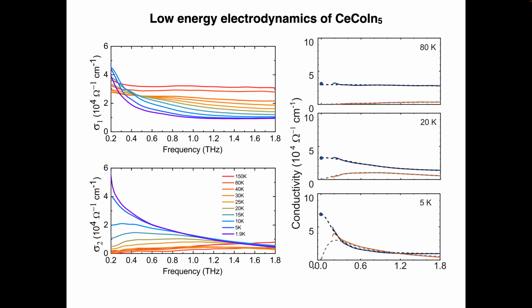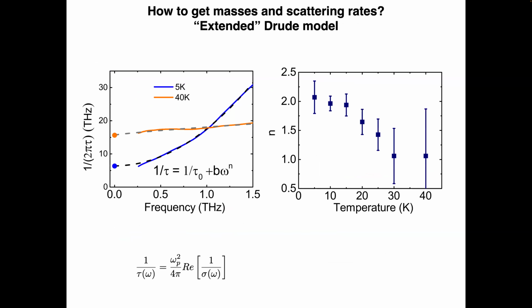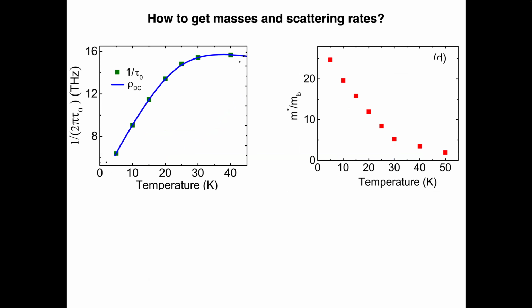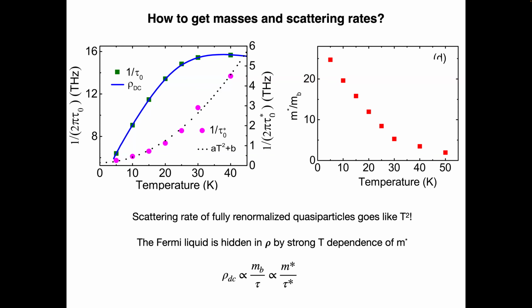And so you could infer from this, again, there's no interpretation here, it's just from basic definitions, that there is a large part of the current which relaxes with a rate which corresponds to that width right there. Now, linear in T resistivity, Planckian dissipation in cerium cobalt indium 5, but when you look at this in the details, let me put this plot there. Yeah, okay, good. What you find out when you look at the width of that little sharp feature at the lowest temperature is that it actually goes, and that's plotted right here, like T squared.